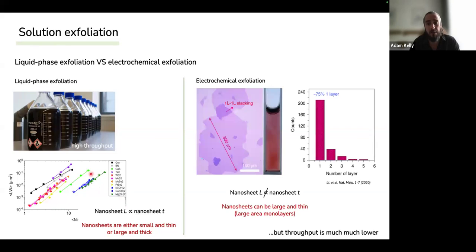With electrochemical exfoliation, we get very, very large area monolayers. So if you're skilled with your technique, you can get up to 75% monolayers in the dispersion at the end. But as you can imagine, the throughput is far, far lower.